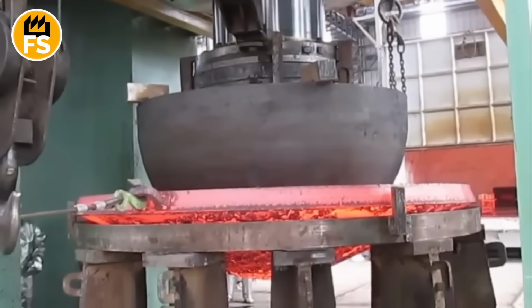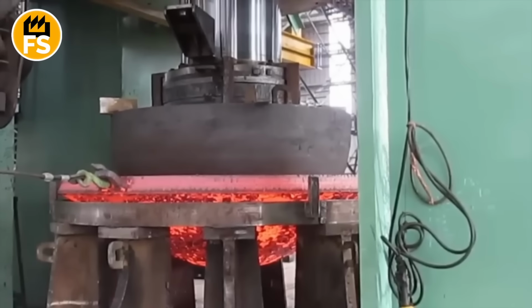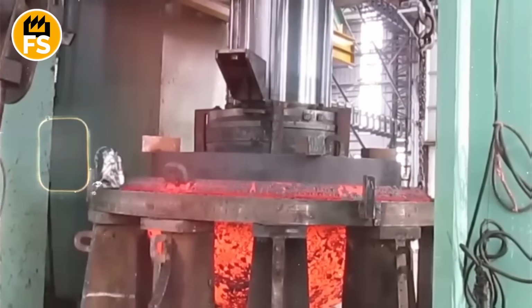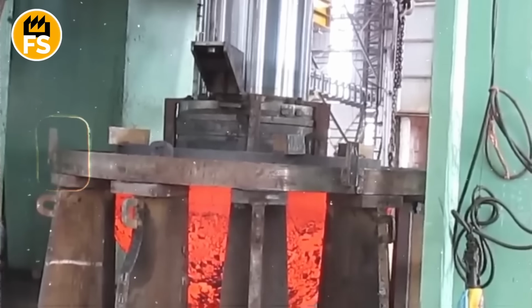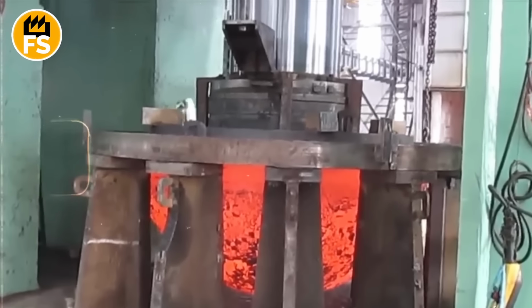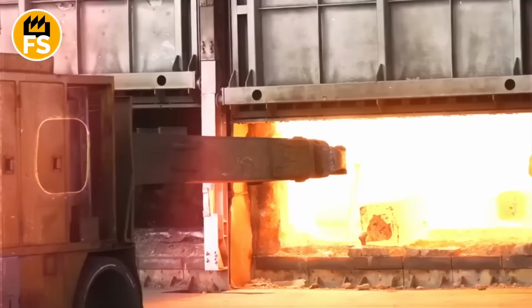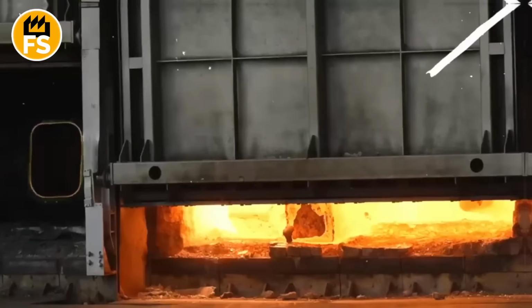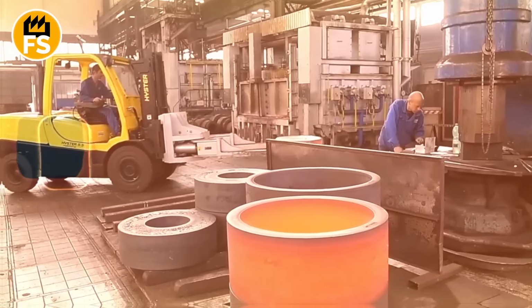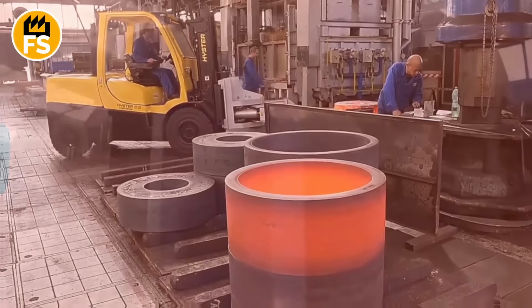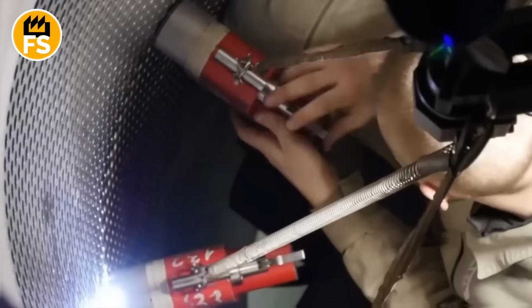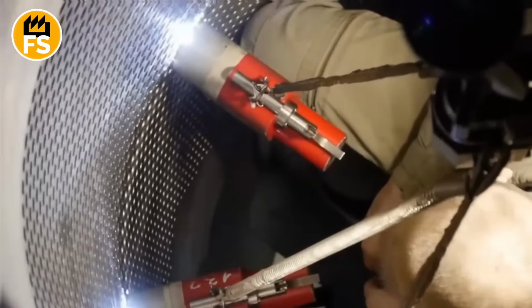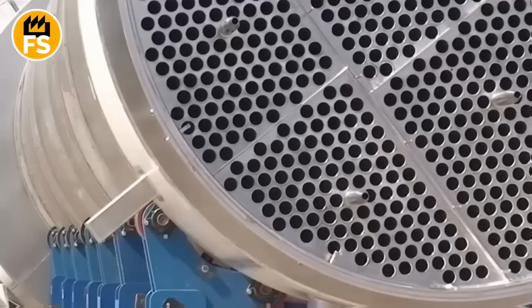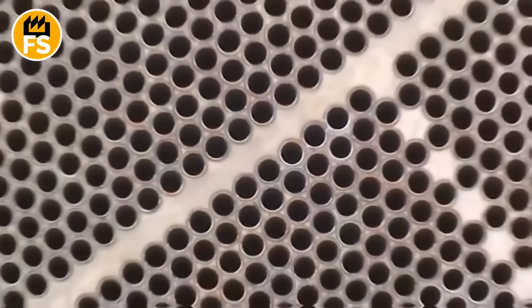Once, the pancake buckles. Twice, deeper still, 3 times, almost a hemisphere. Each pass takes 10, maybe 20 seconds because it cools fast, so back into the furnace and repeat. Then with a hammer, like in a blacksmith shop, they pound out the curve to make it even. Cool it slowly so it doesn't crack, normalize it in the furnace for strength, and ultrasound scans the inside, like an X-ray, catching bubbles or cracks. The finished head withstands pressure up to 500 atmospheres.